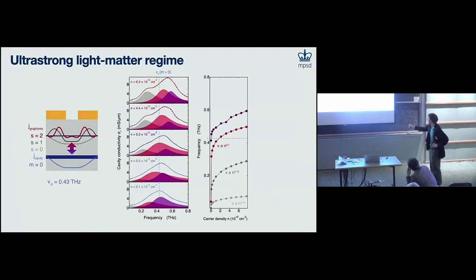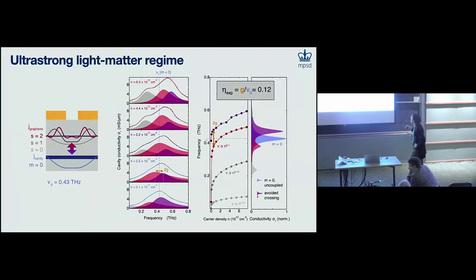Once again, the lowest order one, n to the 1/4, is fine, and then they become suppressed as you go up. But what's interesting is we can now start examining what's happening when you're crossing the cavity mode frequency. And what we find is that there is, in fact, an avoided crossing that's forming. From the size of this avoided crossing, we are just barely into this ultra-strong coupling regime. We've exceeded this 10% threshold.